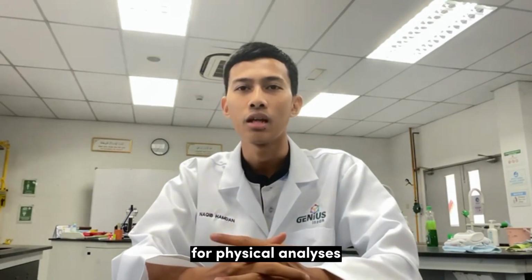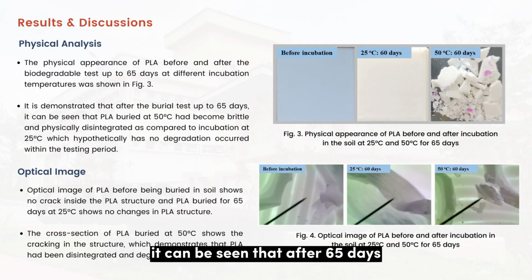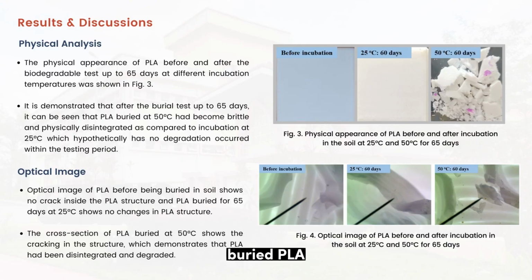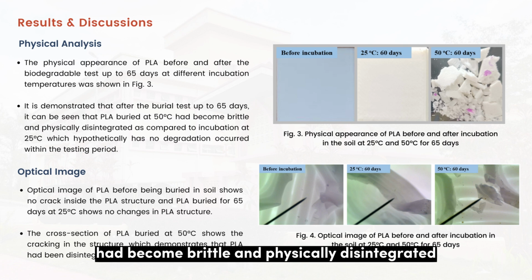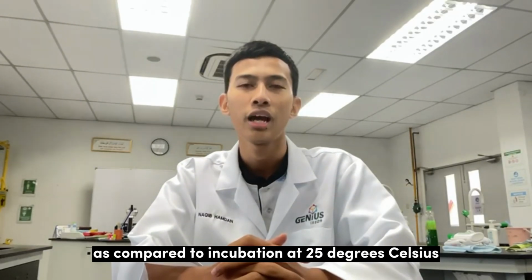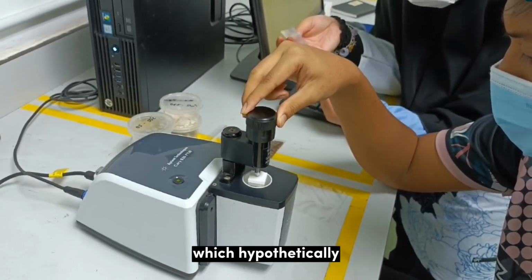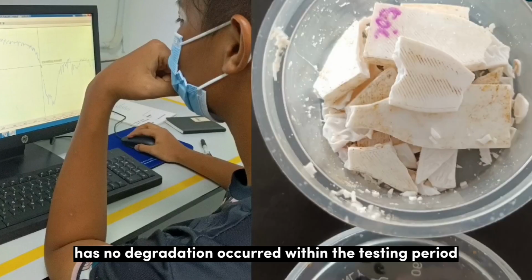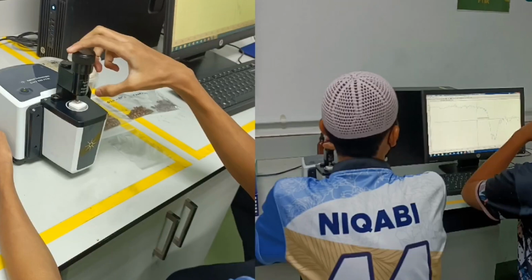For physical analysis, it can be seen that after 65 days, the buried PLA at 50 degrees Celsius had become brittle and physically disintegrated, as compared to incubation at 25 degrees Celsius, which hypothetically had no degradation occurring within the testing period.